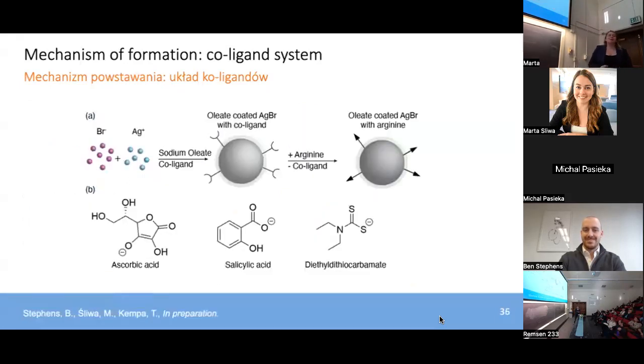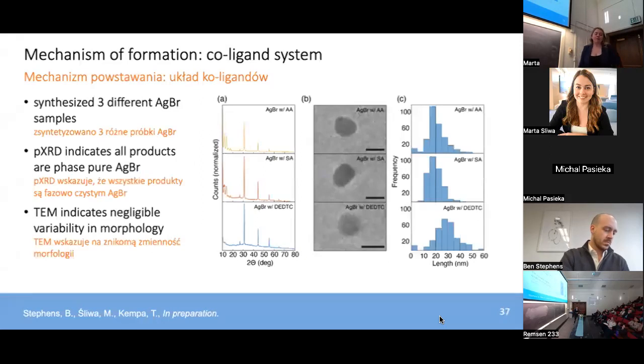So to test this theory that ascorbic acid is acting as a co-ligand, we figured that we should also be able to make silver bromide host nanoparticles that function as the producer of the silver bromide host if we switched out that co-ligand for analogs of the ascorbic acid. So we synthesized silver bromide with 2 analogs, salicylic acid and diethyl dithiocarbamate, which I will not keep saying in this presentation. I'm going to refer to it as the carbamate moving forward. And we saw via PXRD and TEM investigations that no matter the co-ligand that we use, we're able to form spherical, well-stabilized silver bromide host nanoparticles.